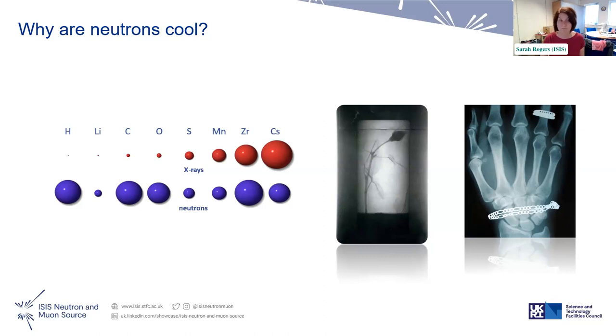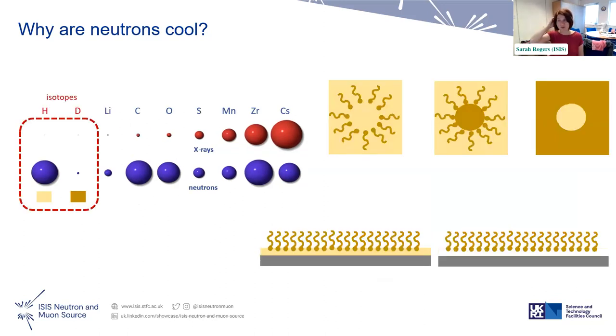The trick I talked about with hydrogen and deuterium, we typically talk about that because I'm a soft matter person. So often swapping in heavy water or deuterating a hydrocarbon material is the easiest contrast to change. You can swap the isotopes over for hydrogen and swap it for deuterium, and you can see the interaction changes totally. So this very strong interaction you have with hydrogen goes away when you have deuterium. And so then it allows us to play these tricks with isotopic substitution, where you can hide and highlight different parts of the system that you're interested in.